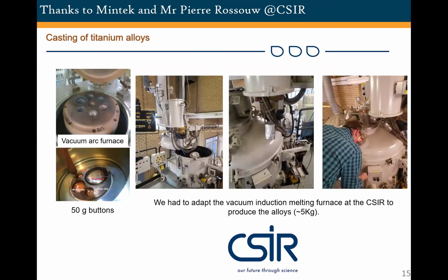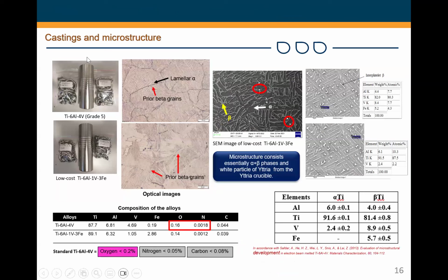Thanks to Mintek and thanks to Pierre Rossouw at CSIR, we started with button samples of about 10 grams. Then we increased it to about 50 grams. When we had more funding, we were able to produce 5 kg of this alloy. And these are pictorial evidence of some of the processes that we took when we were trying to produce this alloy. So we were able to make the alloys, and this is what the 5 kg ones look like.